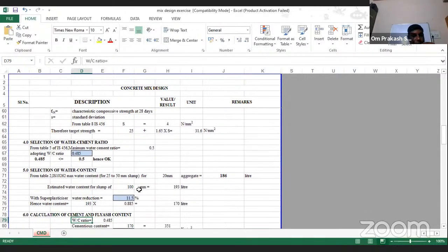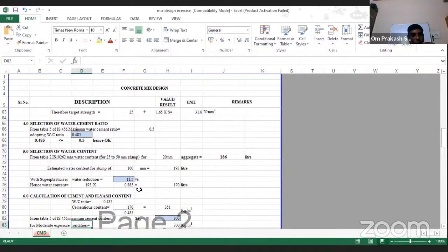Now, coming to the selection of water content. For 25 to 50 mm slump and maximum nominal size aggregate 20 mm, our water content is 186. If we use 10 mm aggregate as nominal maximum size, the water content will be 203. And this 186 is for 25 to 50 mm slump. And what is our requirement? Our requirement is 100 mm slump. Means we have to increase the slump by 50 mm.